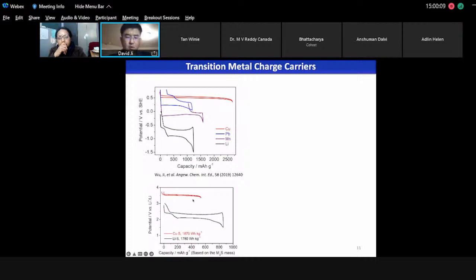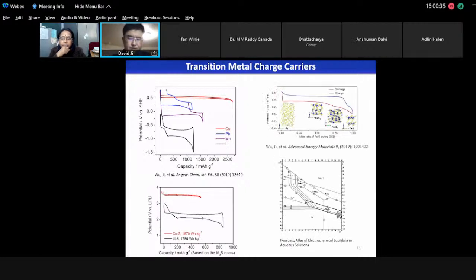So overall, if we don't consider the anode this time, we just consider the energy of the cathode, and the copper sulfur system is more energetic than the lithium sulfur system. And these are not theoretical. These are all measured. These are all experimental results. So two more features I want to highlight. Extremely small, minuscule polarization for copper. Almost no polarization for copper.